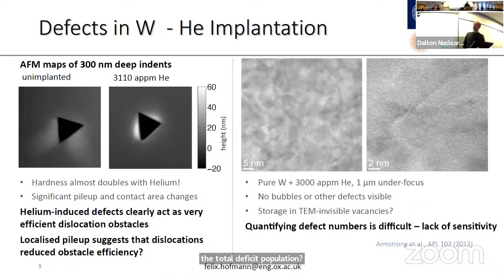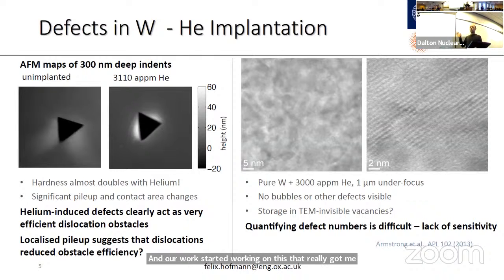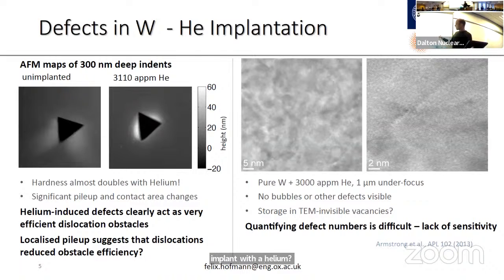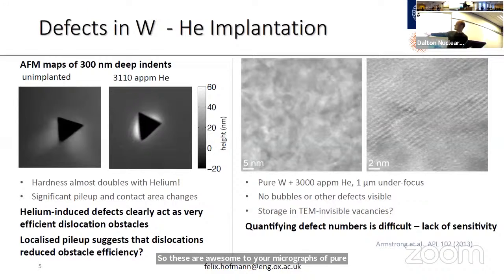So this slide actually shows some data right from the start, when I started working on this, that really got me interested, because one of the scenarios where you have almost exclusively these tiny defects is if you implant with helium. So these here are some TEM micrographs of pure tungsten implanted with 3000 appm of helium.